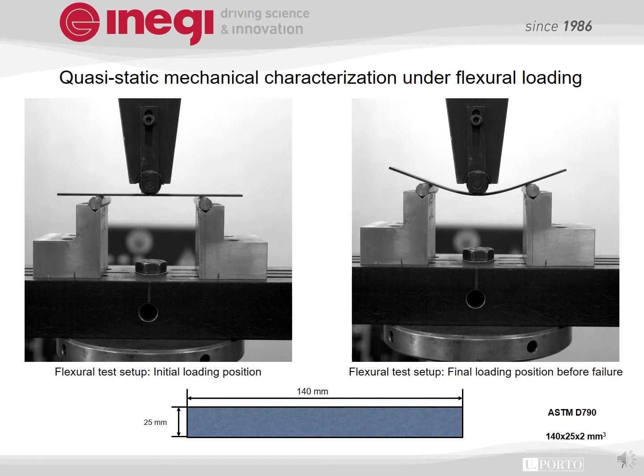Quasi-static mechanical characterization under flexural loading. Flexural tests were conducted on reference and EC electrical conductive specimens according to the test standard ASTM D790. Dimensions of the specimens were 140 by 25 by 2 mm as the length, width, and the thickness of the specimens. Total 5 specimens were tested according to the test protocol.